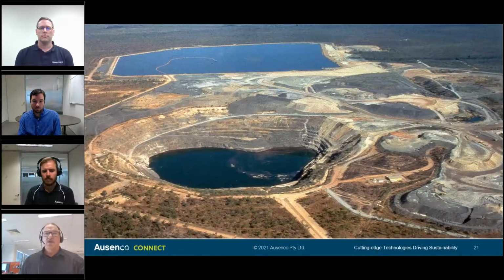Next slide. So this is an interesting slide, and I think it's important to understand that we have two scenarios here. We have a mined out pit, and we have the TSF in the background. Due to the geometry of the mined out pit, depositing tailings into the pit generally results in a subaqueous deposition and a significant depth of low density material that will not consolidate, or consolidates very slowly. So thickened tailings prior to deposition will reduce the amount of water put into the pit, and with good management will enhance the possibility of maximizing the density of the deposited tailings.